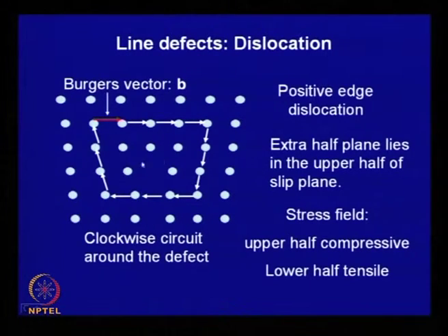In reality this stress will not be 0. When you move this dislocation, it has a surrounding stress field, and this stress field will interact with the periodic stress field existing within the crystal. So, to move this stress field within a periodic stress field, you will need a small amount of lattice friction stress, which is to be overcome. And this stress is much smaller than the ideal strength of the crystal.